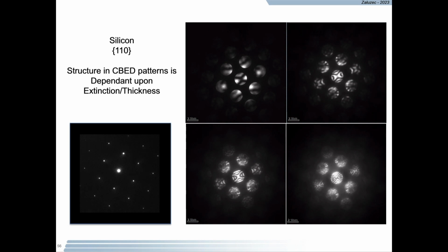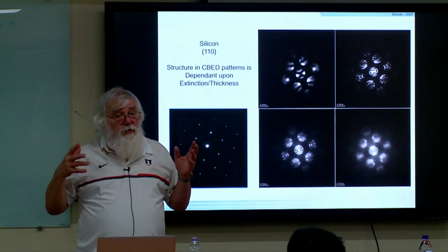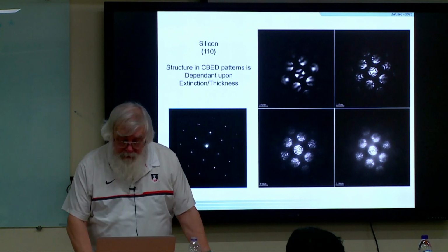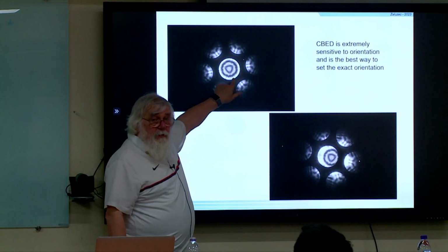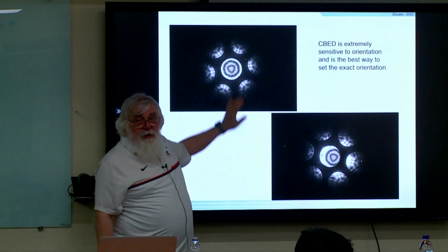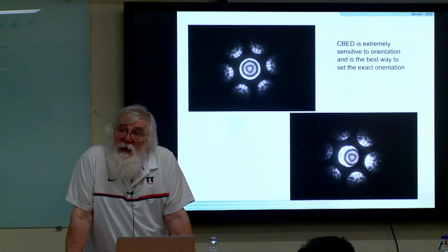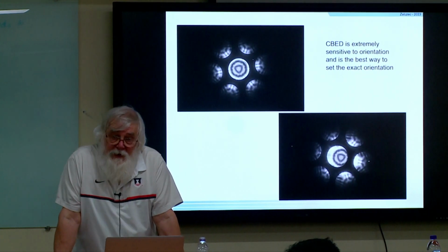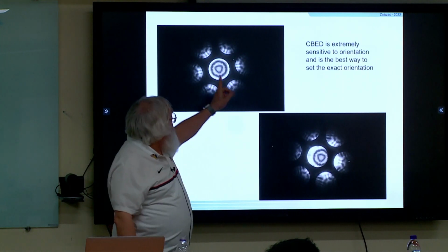This information, by the way, for those of you interested in the physics of electron scattering, means you can measure the structure factor of the solid. The other thing Hamish will tell you about is high-order Laue zones, high-order scattering. If I look just in the 0,0,0 disk, the straight-through beam, and the sample is relatively thick, you see a lot of structure in there. That's very important crystallographic information. It gives you information about the 3D structure. It is also very useful for accurately aligning my sample.